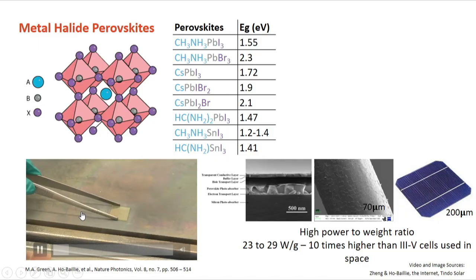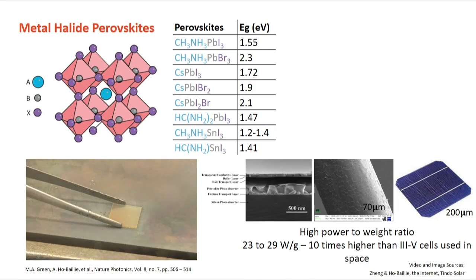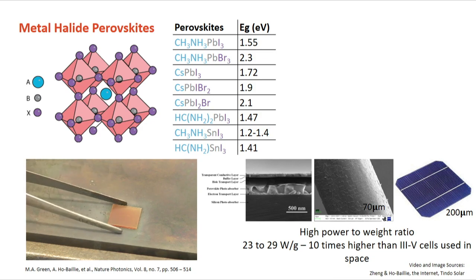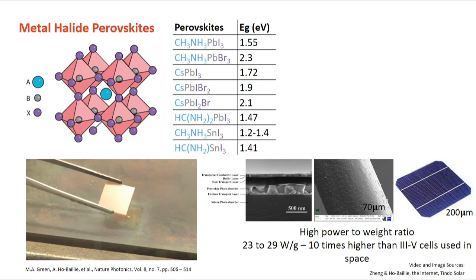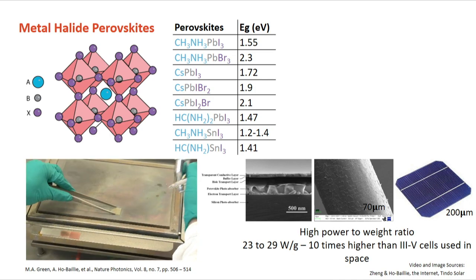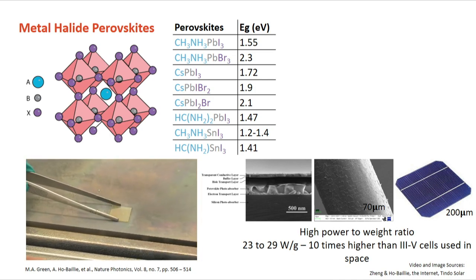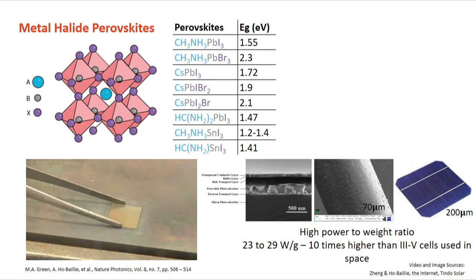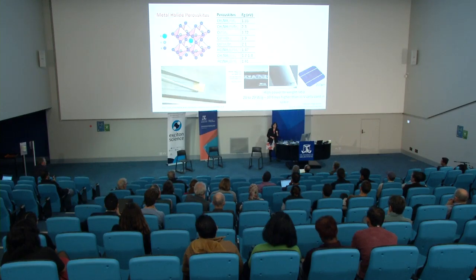Another attractive attribute of the perovskite cell is you can actually fabricate it using a solution process. So you mix the AB salt or the BX salt, you put it in the solvent, and you can spray it, you can print it onto a piece of substrate, which can be flexible or glass. You give it a temperature of 100 to 200 degrees, not the 1,000 that you would use for silicon, and voila, you get the photoactive material here. So you can see the color change. That means it's absorbing orange light and above.